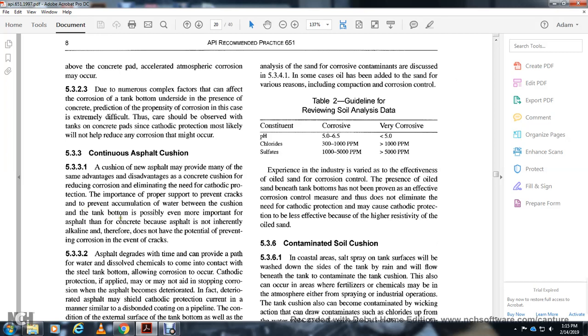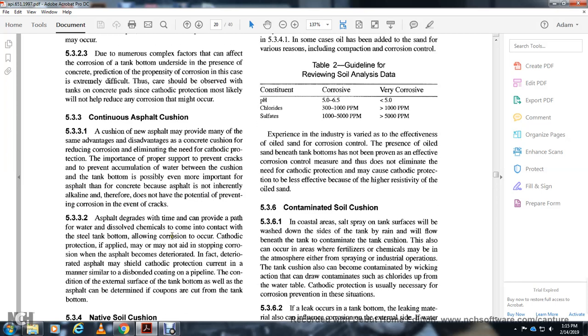Even more important with the asphalt, compared with the concrete, is that asphalt is not inherently alkaline, therefore it does not have any potential for preventing corrosion in the event of cracks. Cracks form as the asphalt degrades with time, providing a path for water with dissolved chemicals coming in contact with the steel tank bottom, leading to corrosion.